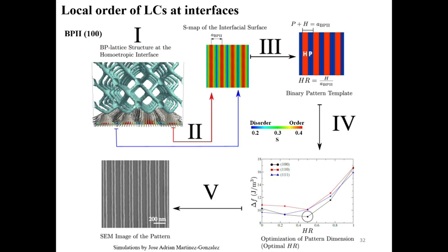And so we interpret the formation of the liquid crystal as a pattern which has alternating homeotropic and planar regions. By calculating the overall free energy of the system, we found that when those planar and homeotropic stripe widths are equal to each other, that is the lowest energy point. That is also the reason how we arrived at this pattern design to stabilize that specific blue phase 2 100 plane. And following the same